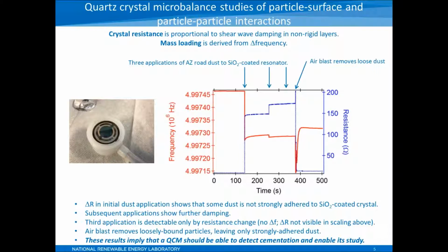Another interesting aspect of this experiment was that it's a self-limiting process. With increasing doses of dust, you see less and less response. In fact, on the third application, there's very little change and no discernible change in the frequency, although there is a small change in the crystal resistance. And then finally, I just used a little portable air duster to remove the dust, and it turns out that you see the crystal resistance drop all the way down to where it was initially, but the frequency doesn't return to its origin, which means we're left only with very tightly bound dust. So this to me was really interesting and showed that there's a number of things we could get out of experiments using this quartz crystal oscillator.